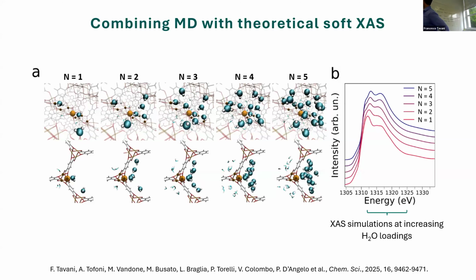And you may see that there is quite a change. I mean, going from the XAS spectrum shown here in red, calculated for the lowest hydration level, there is like a bump. Again, these are spectroscopy terms, so sorry for this. But going from the lowest hydration level to the full hydration level, there is an increase of this feature here, which becomes much more intense. And this for XAS people is considered a very significant change. So this is a surprise because magnesium is not changing its coordination geometry. It's always octahedral, but still we have significant variation of the local structural properties without a change in coordination environment.